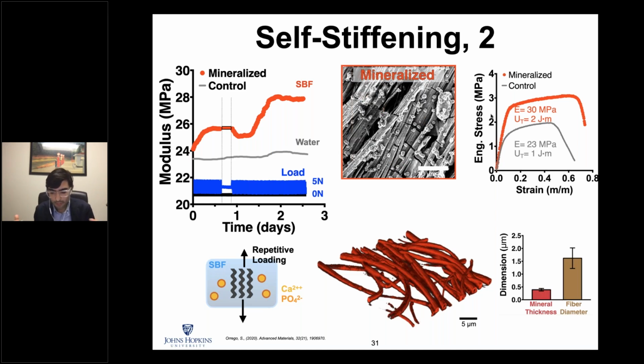There's also some mineralization between fibers. Now, if you measure the residual stress, the stress-strain after, we see that the red one is after mineralization. We see an increase of strength, increase of modulus, and also an increase of toughness, compared to a control that pretty much remains the same.